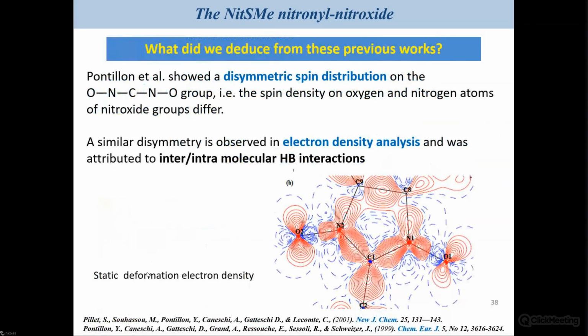So, okay, what is the conclusion of that? You observe, if you do spin density analysis, that the spin distribution is not identical for the two arms of the function. If you do charge density analysis, you observe again, as you can see on that map, that especially the lone pairs of the oxygen atoms are not identical. So it means you have a dissymmetry that comes maybe, this is what we imagine, from the different hydrogen bonds that are present for O1 and O2 in that system.